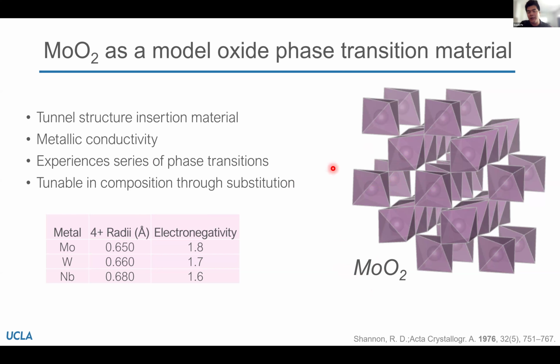And so by using this as a model system, we can alter the material at the macro level. There's been a lot of work done on nano-size MoO2 and how that affects the phase transitions, but we could also tune the composition chemically through substitution. And so in this table here, I've shown potential transition metals that you're able to substitute for molybdenum in the structure, and we'll see how that can affect the performance.